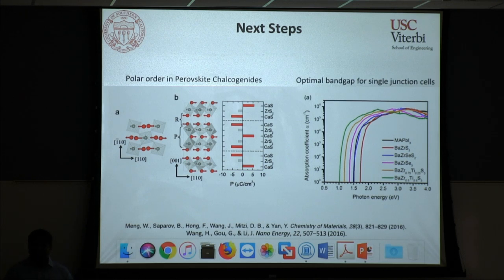to us because of the predictions on the bulk photovoltaic effect, where if you have a polar order in a semiconductor, even though your polarization need not be maintained very successfully, if you shine light, this local polarization will help you split your excitons into electrons and holes in different directions, and hence it could help with charge separation much more efficiently. So this was something that we were a little bit interested in.